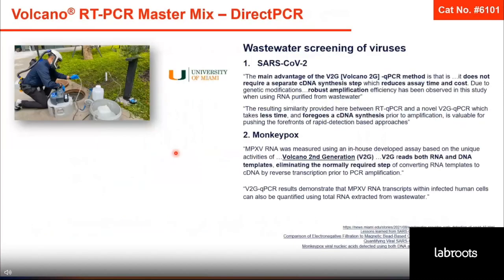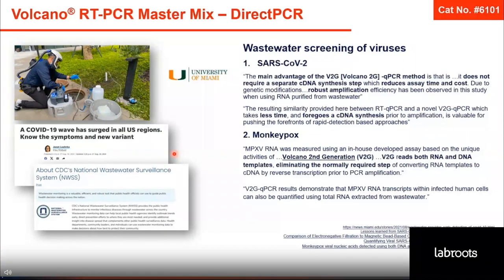This is an interesting example of how Volcano can be used in screening for infectious diseases. The example is coming from the University of Miami, where they established a screening assay using Volcano as a master mix. The screening assay comes from wastewater, where they screen for SARS, for COVID infections, and they also screened water for monkeypox virus infections. So what they observed is that using Volcano, they could save a lot of time, first of all, because they were able to use extracts from wastewater directly as a sample in the master mix. And secondly, there was no requirement of an additional cDNA synthesis step. So they saved a lot of time in the qPCR reaction.